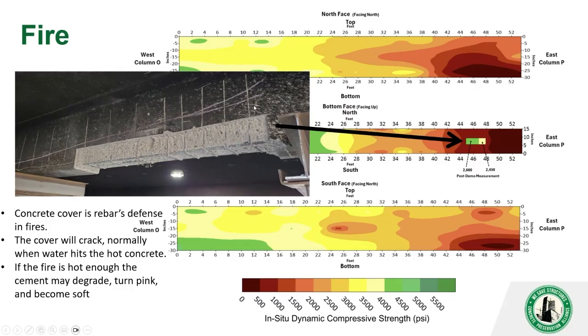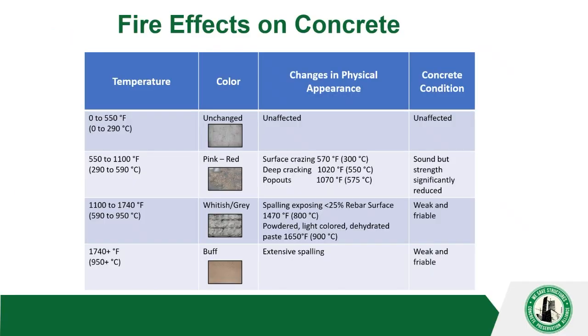And what happens a lot of times is the concrete on the surface gets cracked when they spray water on it, right? So it shatters, and then your concrete surface sounds bad, but inside it may not be. Just something for you to think about. And then if you look at fire, the color of the concrete can tell you how hot it actually got. If you have this pink, red, that's where you start having some problems. And if you have exposed reinforcing steel, the cover's flaking off, you might be at a point where you might have to remove that element or at least repair it, maybe strengthening it. And if it turns buff, there's hardly any strength anymore in the cement. So you're going to have to replace the element. So much for fire.